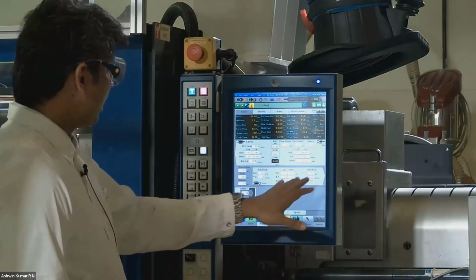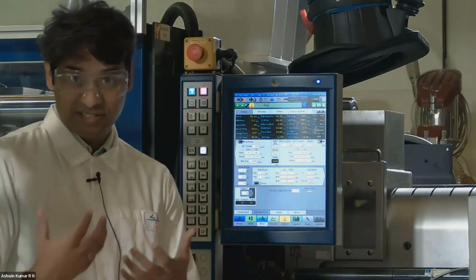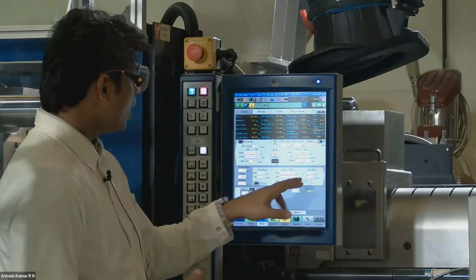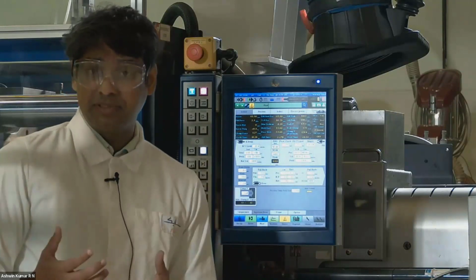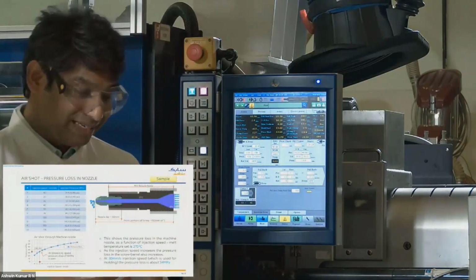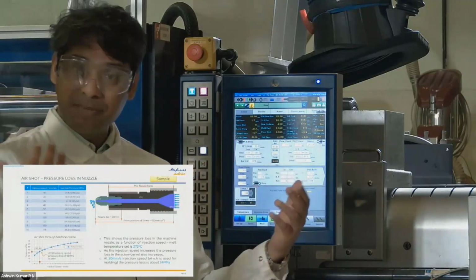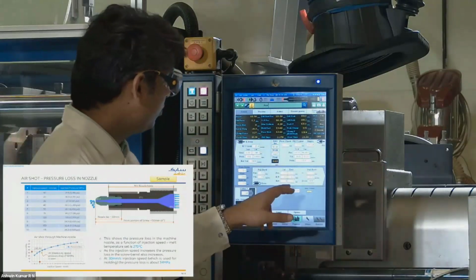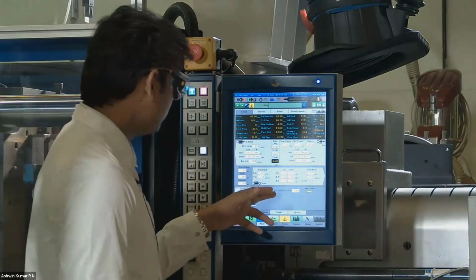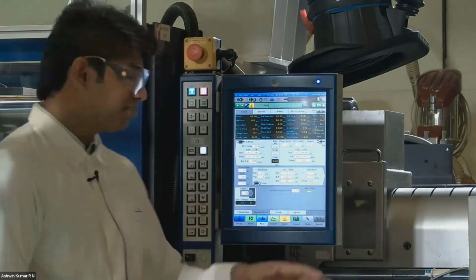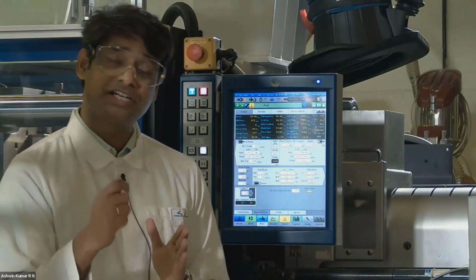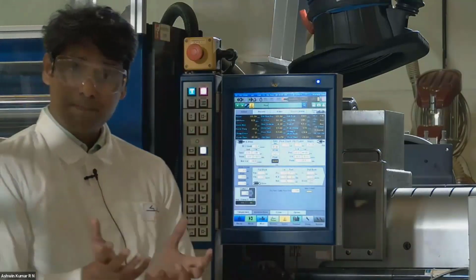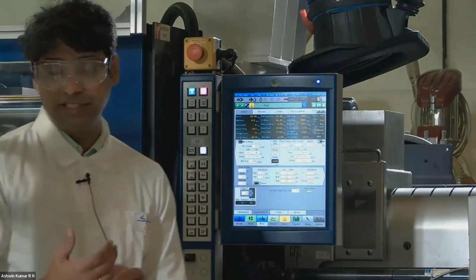Another thing I want to highlight is the dosing stage, the refill stage, what you call the back pressure and the screw RPM. It is also really important to make sure that there are not many variations happening in the melt temperature when it's prepared in the barrel. So for that, we are using about 50 RPM screw speed with 2.2 megapascals of back pressure. That is resulting in about 21 seconds of dosing time, which is still under our control limit of cooling time. And I'm also getting an additional 15 seconds for the dwell time where the melt temperature actually stabilizes. So with these boundary conditions, let's look at the output we usually monitor.